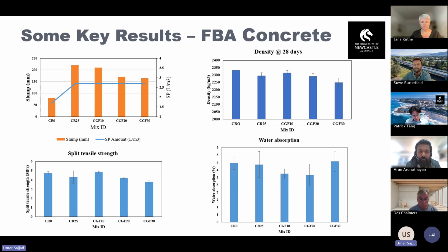Then we have water absorption. Although the initial water absorption of furnace bottom ash as a raw material is high, when we utilized it in concrete, the results we obtained are promising: for the 10% replacement mixture, we have slightly lower water absorption compared to other concrete mixes.